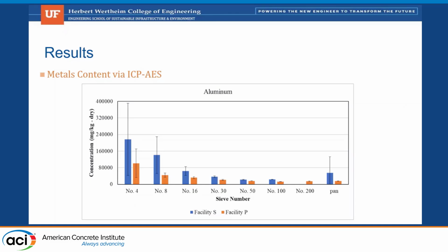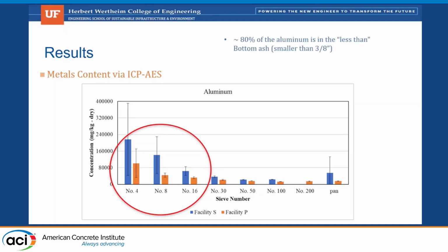One of the things that we found out that was pretty important, we feel, is that when you look at the less than size, we see that the majority of the aluminum is in the greater fraction of the less than material. So I split my 3/8, and I have most of the aluminum migrating in the number 4, 8, and 16 sieve. Okay, so if we were going to do more work and reduce that and really try and focus on the aluminum, that's where it resides. And again, that's a product of the non-ferrous removals at the particular waste to energy facility. That's going to change with more advanced non-ferrous metals removal in the future.